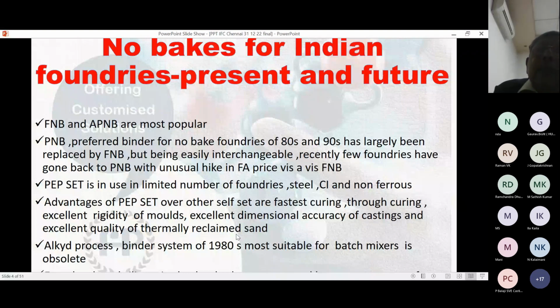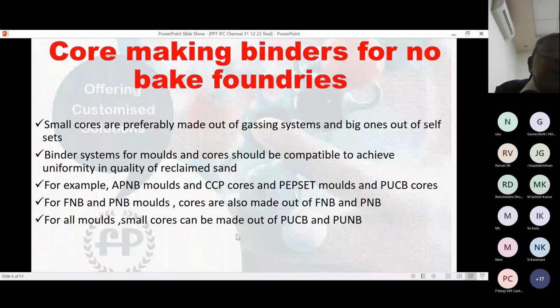So we have talked about the mold making binders for no bake foundries, particularly in continuous mixer. Cores in these no bake foundries are preferably made out of gassing systems and big ones out of self-sets. Binder systems for mold and cores should be compatible to achieve uniformity in quality of reclaimed sand. Just like that, Alphaset molds with carbon dioxide cured phenolic cores and PEP set mold with cold box core. These are compatible and you can reclaim together, so contamination does not matter.